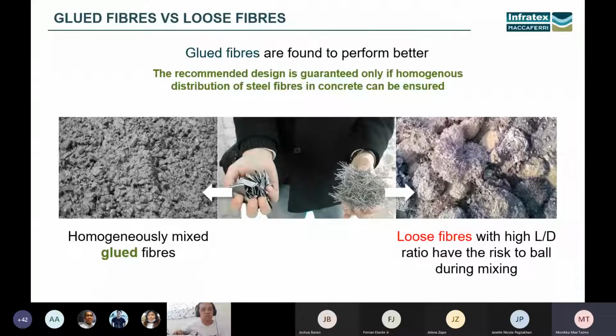Okay, so this one is the difference between the glued fibers and the loose fibers. As I've said earlier, Dramix steel fibers are glued fibers. Why? Because they are found to perform better. Loose fibers can have problems such as balling. In using glued fibers, you just pour them directly into the concrete and then they will scatter through the concrete mix. So we will avoid balling during mixing.